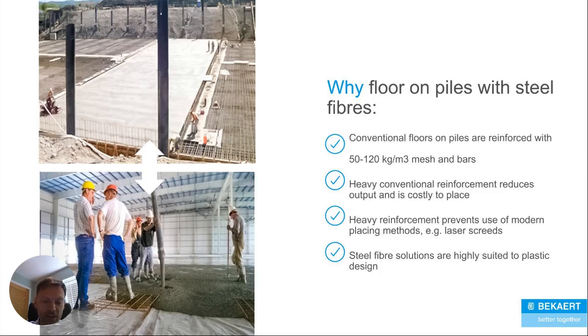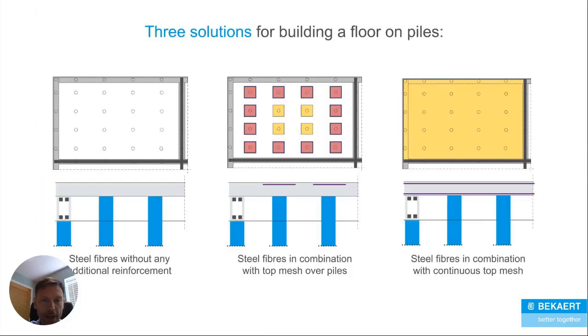And because of the congestion of steel, particularly with the steel being in the top as well as the bottom, you can't direct discharge concrete from trucks. You would need to pump, which is not a problem, but again, it adds to the financial elements and also it slows down the process. By using steel fibre concrete, it's possible to eliminate a pump in some cases, in most cases, and usually it can be done cheaper and quicker, but with the same performance.